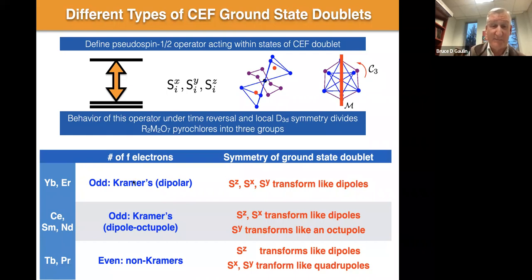The other possibilities are you can also have an odd number of electrons, as you have for cerium 3+, but because of the symmetry operations relevant to the local geometry, two of the components of the pseudospin-a-half degree of freedom behave like magnetic dipoles, and the third behaves like a magnetic octupole. And then there's a third possibility, which only comes up when you have an even number of electrons, where one of the components behaves like a magnetic dipole, and two of the components behave like quadrupoles. So in general, these are the three types of spin-a-half degree of freedom you can have in these rare earth type systems.